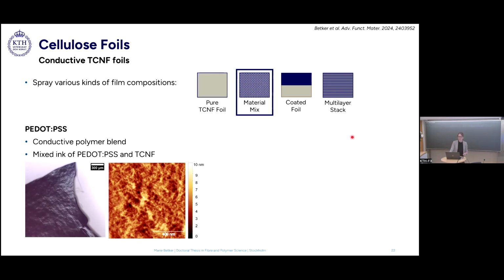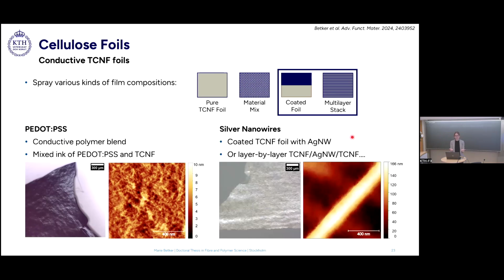But of course, you can also simply take your cellulose foil and coat it. In this case, we took silver nanowires and coated them on top. But you can also make a multi-layer stack: first you spray some layers of cellulose, then some layers of silver nanowires, and so on. And this different composition also affects the properties of these foils. This is what I want to explain on these two examples here.